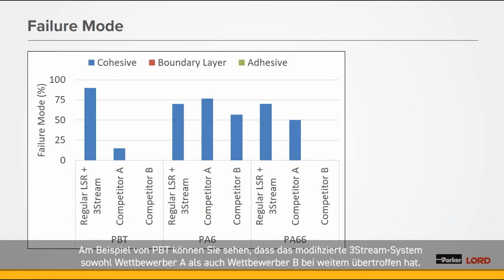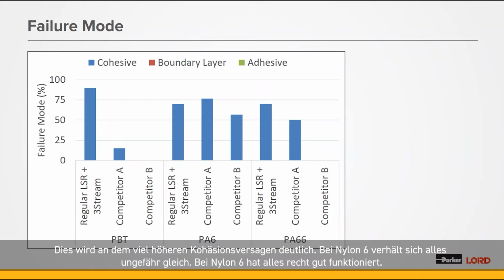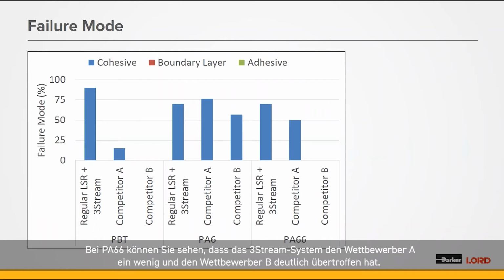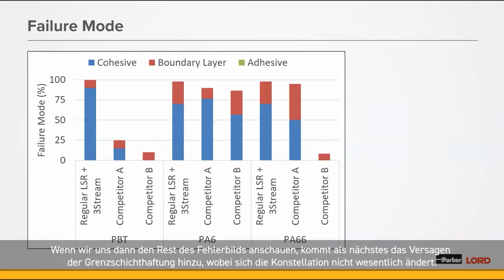So you can see in the example of PBT, the 3-stream modified system significantly outperformed both competitor A and competitor B, and you can see that by the much higher cohesive failure. On the nylon 6, everything is about the same. Everything performed reasonably well on nylon 6. On PA66, you can see that the 3-stream system outperformed competitor A a little bit, and then greatly outperformed competitor B.